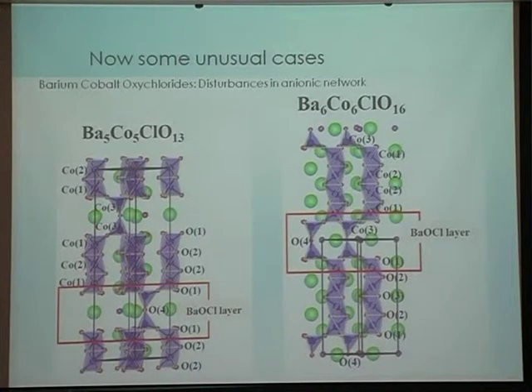Okay? Now, unlike what I wanted to do, I had put in chlorine in place of oxygen. I thought I put in, but it actually did not replace an oxygen. What it did is chlorine stayed somewhere here separately. This is chlorine. It did not get involved into any bonding with any of the cobalt or anything. It remained separate. Now this is particularly the level that I would call BaOCl layer, basically because there is an oxygen, there is a chlorine, and these are the barium. So this is the BaOCl layer. Now the chlorine really did not substitute oxygen. It did get into the lattice, but did not do anything else.